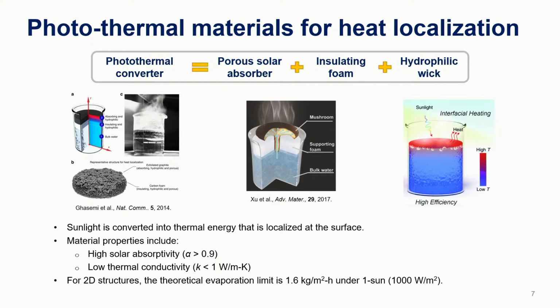So again, the main design criteria for the materials is a very high solar absorptivity. Typically, you want something that's at least about 0.9, and you want a thermal conductivity that's less than 1 watt per meter Kelvin. So a lot of carbon foams can meet those criteria. Now, if you have a two-dimensional structure, the amount of evaporation that you can get is going to be limited, because the sunlight coming in is fixed at 1,000 watts per meter square, and so your evaporation rate is limited to about 1.6 kilograms of water per square meter per hour. So you still need significantly large areas to do this evaporation.